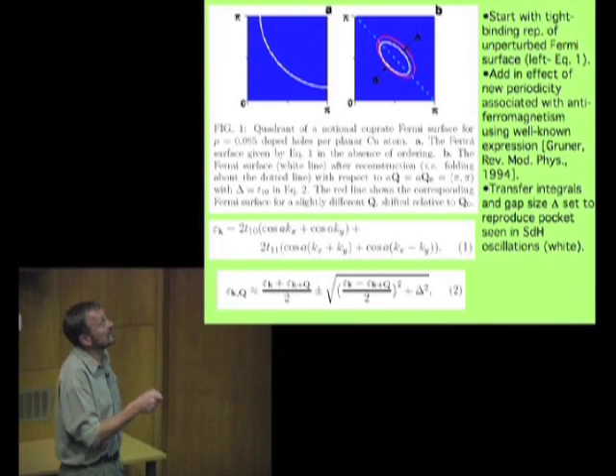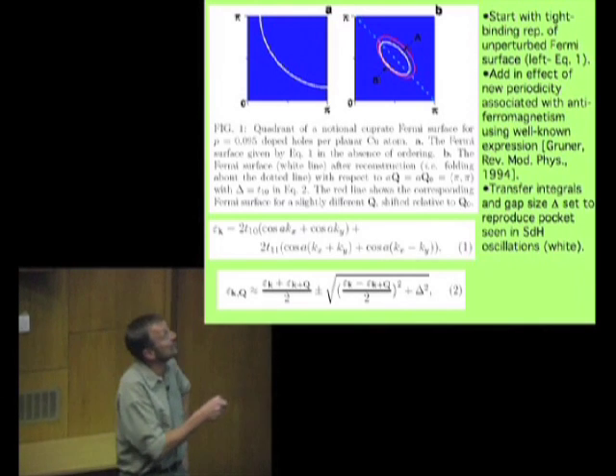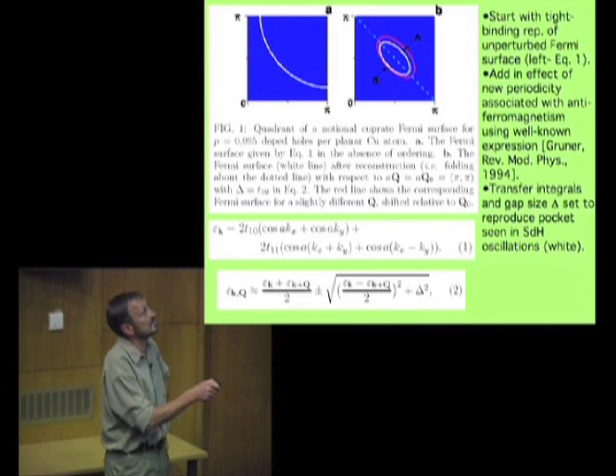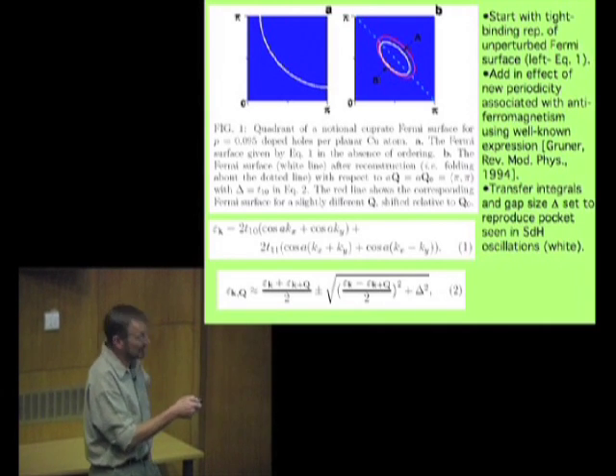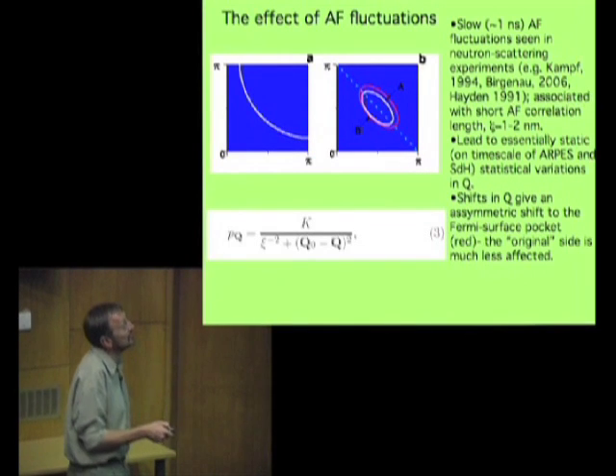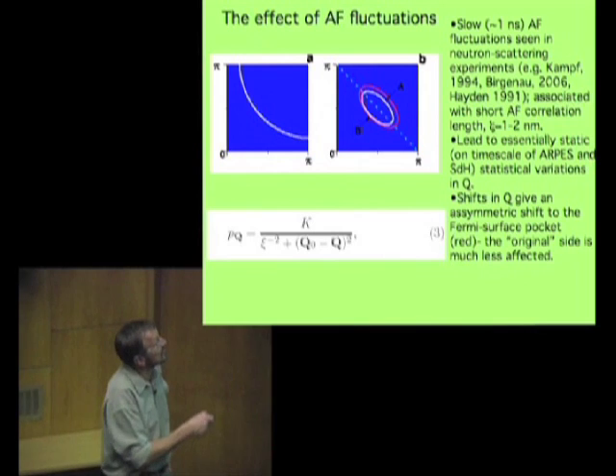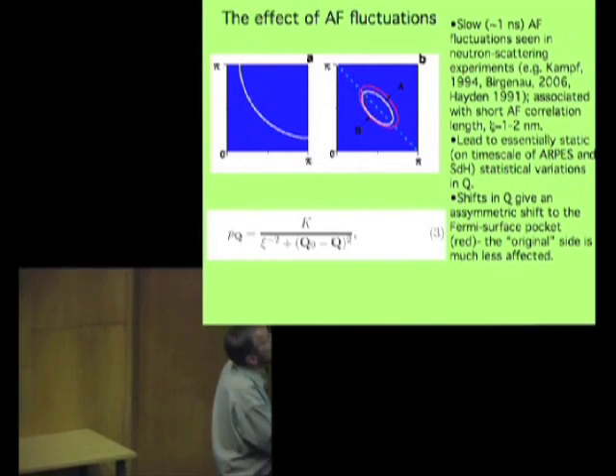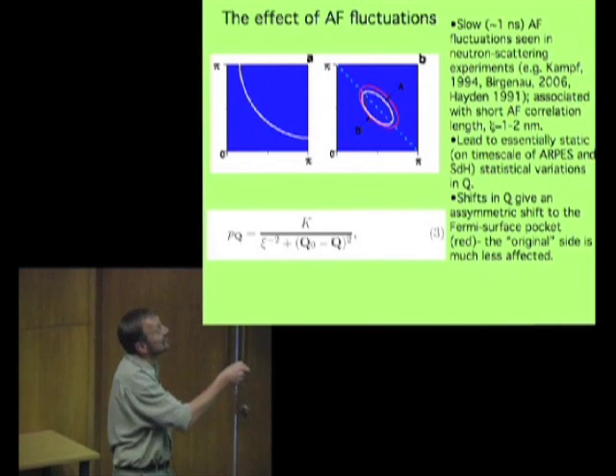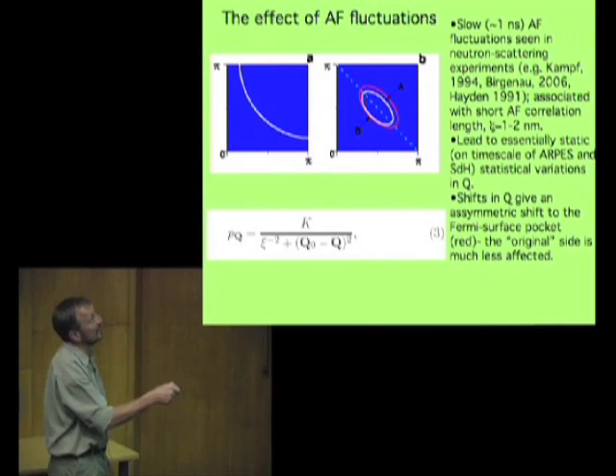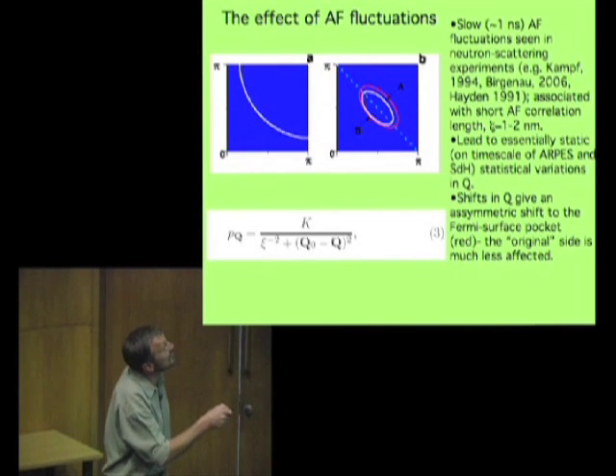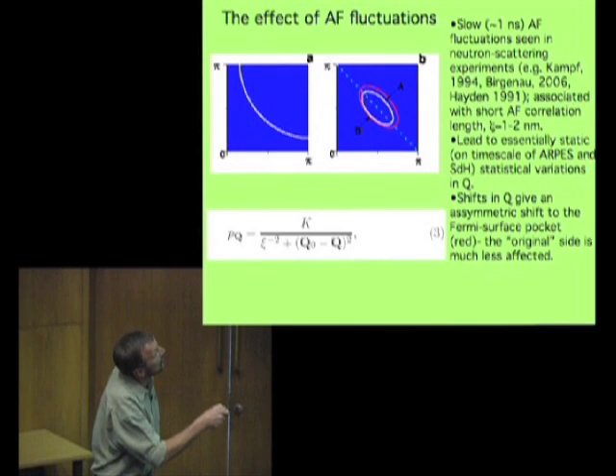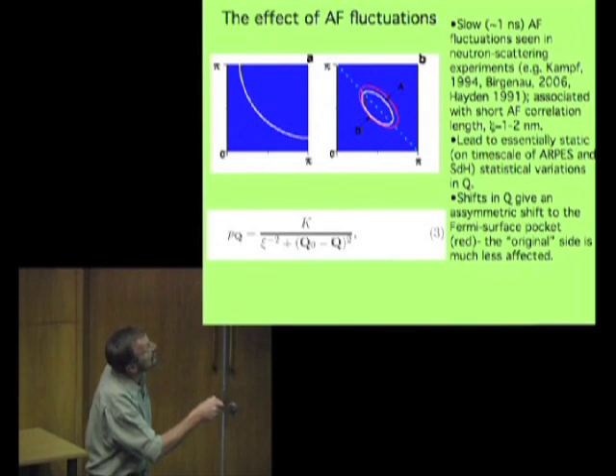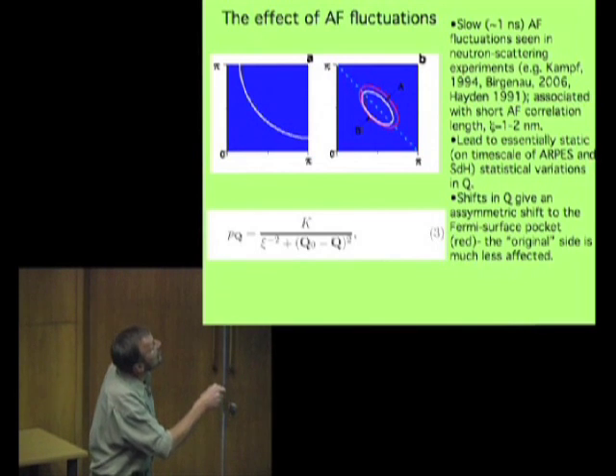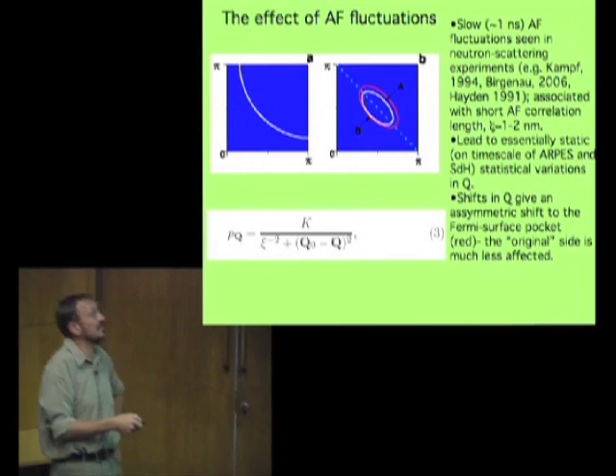So let's suppose then that the neutron scattering measurements are telling the truth, and we have a distribution of these different periodicities in the antiferromagnetism, so that we get not just the white pocket, but the red pocket in some places, and see what effect that has. So basically what we do is we propose that there's a probability distribution of the different shapes of Fermi surface resulting from the moving in and out of this blue dotted line, which is given by the correlation length seen in the neutron scattering measurements. What this is going to do is, look, the original part of the Fermi surface doesn't move very much as you move this blue dotted line around. But on the other hand, the new part that's made by reflecting this original part does move around a lot as you move the periodicity of the antiferromagnetism around.